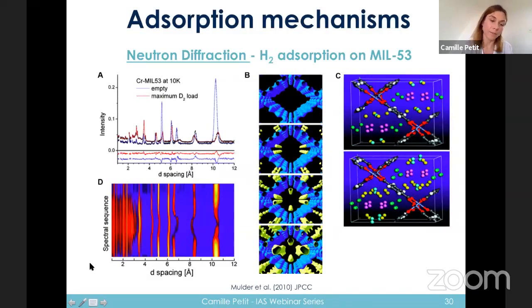And in D here, if you look at the y-axis here, that will be a time evolution. And again, it's a map, so the color indicates the intensity of certain peaks. And what you can see here is that if I take, for instance, the example of that peak here, we have a shift and then a return to the original position. And that pattern here is indicating a progressive adsorption and then desorption. So we're seeing here a reversible adsorption of hydrogen within the structure.